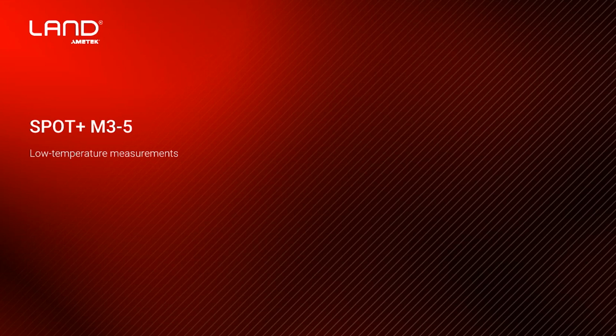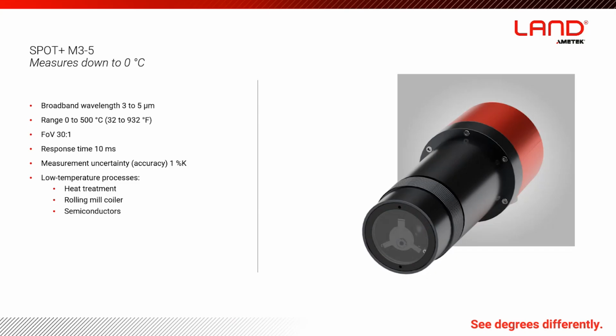The M3 uses a broadband 3 to 5 micron wavelength, and that, as you will remember from my discussion of the Planck function, that longer wavelength allows us to measure cooler temperatures. So we're describing this as our low temperature pyrometer because it's got a measurement range all the way down to 0 degrees Celsius. It can measure 0 to 500 Celsius. So it's ideal for applications like heat treatment, the coiler at the end of a rolling mill, or some semiconductor applications where we're looking at moderate temperatures.